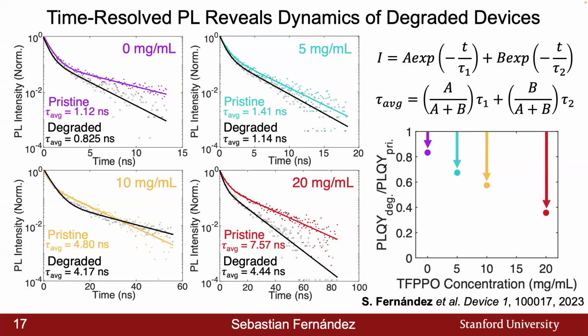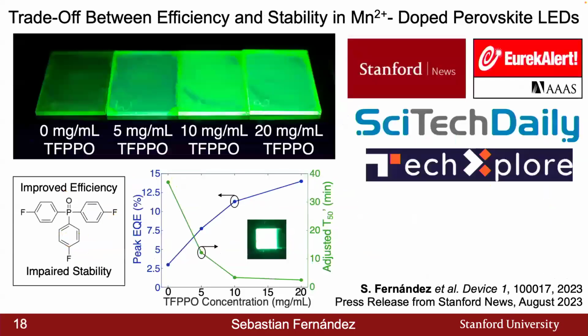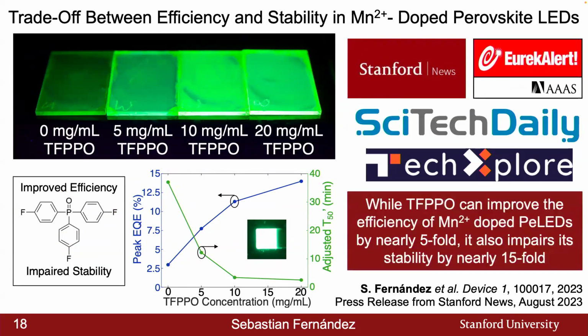Also looking at the photoluminescence quantum yield, both before and after the degradation of these devices, you can see a clear monotonic decrease under identical electrical operating conditions, which together paired with the time resolved luminescence decay measurements allow us to say that the overall emissive efficiency of these devices is decreasing, typically with higher TFPPO concentration. And so in general, we've shown that we can improve the efficiency of these thin films with this TFPPO or phosphine oxide additive system, but it unfortunately does come at a great cost in stability, nearly 15-fold.